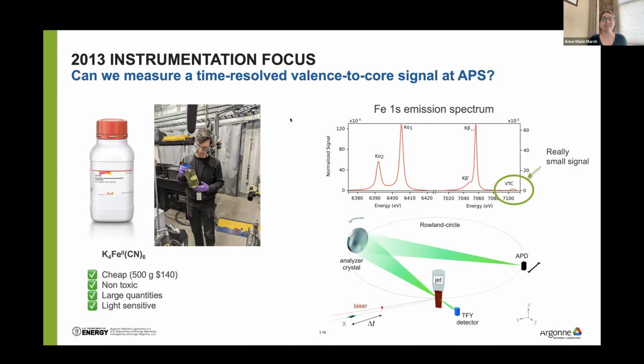And the valence-to-core signal is teeny tiny, and we had our Johann spectrometer at megahertz rates. Is this even possible, to measure a transient signal? We needed a complex that was light sensitive, but that we can make in huge quantities, because we're going to have to acquire for a really, really long time. Ferrocyanide fit the bill.